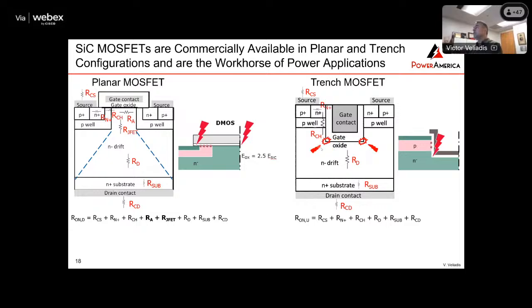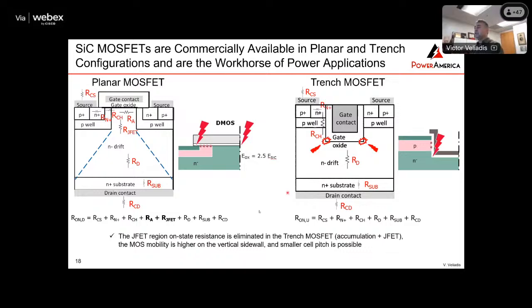at the corner of the gate oxide that are very prone to breakdown because of the very high electric field concentration in this area. So the JFET region that contributes to the resistance is eliminated in the trench MOSFET, and the MOS mobility in the vertical direction is higher, and you have a smaller device extent, which means you get more devices per wafer, and all those reduce the cost. The drawback, of course, is that in the trench MOSFET, the blocking voltage capability can be lower because you have the high electric field at these corners, so you're not going to get to the full capability of the drift layer unless you do certain design modifications.